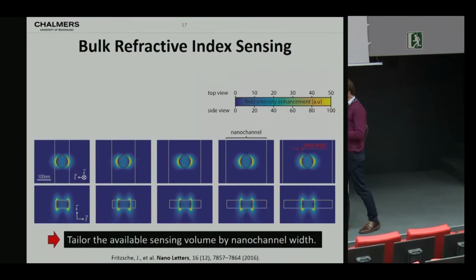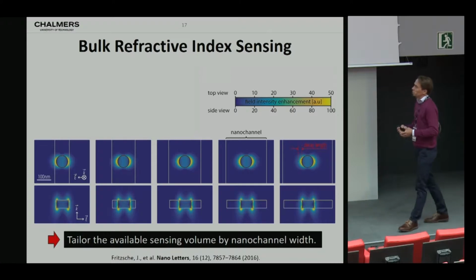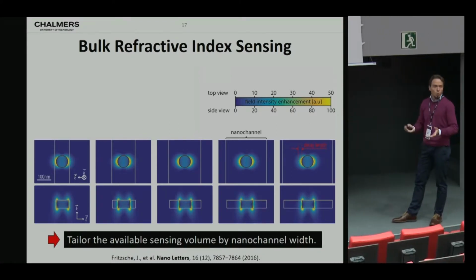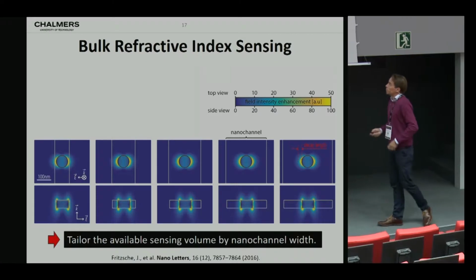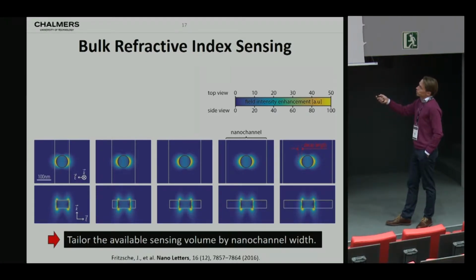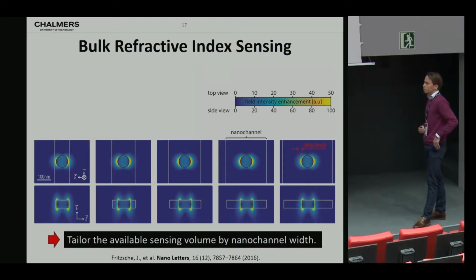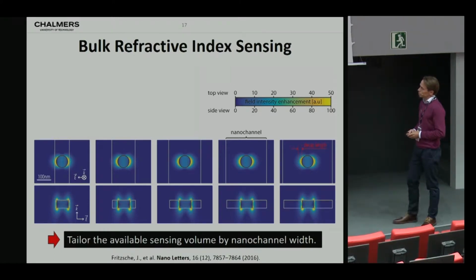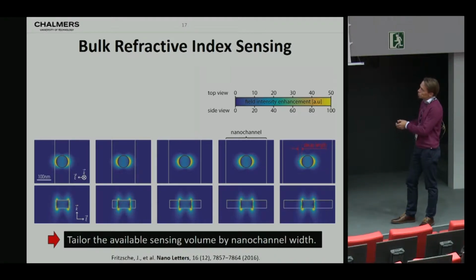So, with this system at hand, what do you do? Well, you start out with the most simple kind of characterization to get to know what you have created. And what would that be for a plasmonic sensing structure? Well, it's to measure the bulk refractive index sensitivity. But before we do that experimentally, I think it's instructive to look at some FDTD simulations of this system. Because what I essentially want to show you is, as you change the width of the nanochannel, which is indicated here by these white lines, you are able to exclude or to occupy some of the sensing volume, which is defined by the enhanced near field, by the channel walls.